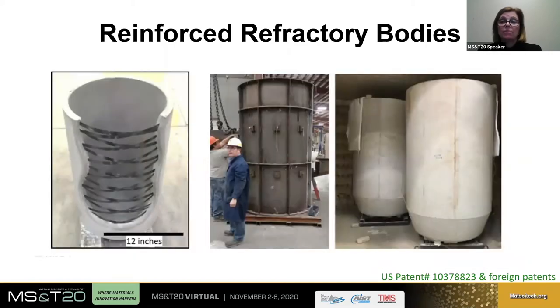We have applied a similar approach to induction furnace refractory crucibles. These precast, pre-fired composite crucibles are used in furnaces where the refractory cracks heavily due to thermal differences. The thermal difference can be from the top to the bottom of a crucible due to low metal liquid levels, or it can be due to slow pouring operations where the exposed backside of the crucible cools more quickly than the side that's underneath the metal.